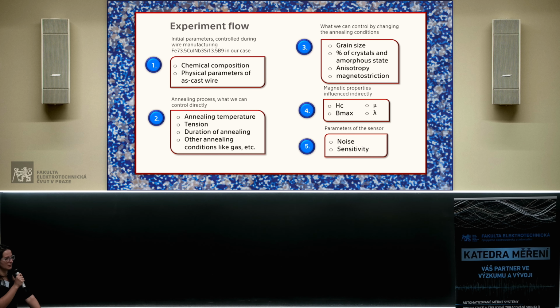So, a couple of words about the experiment. What we cannot change is the chemical composition, because this wire is ordered from the Romanian Institute of Physics, and it's a ready wire, an as-cast alloy, with a diameter of 120 micrometers. But while processing this wire, we can change certain parameters like tension, applied stress, annealing temperature, duration of annealing, and some parameters like gas, etc.